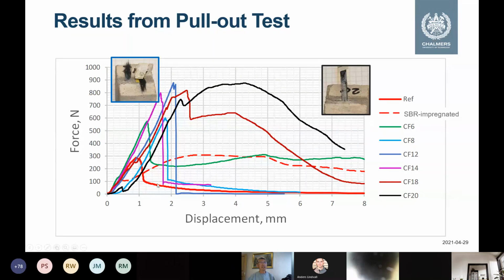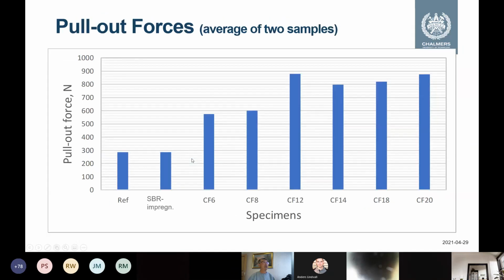The red one is the ordinary fiber without nano treatment. But all of the nano impregnated fibers show much higher pull-out strength and also a much longer displacement, which is an indication of very good bonding. This one is a commercial SBR, a kind of rubber impregnated fiber. But our nano impregnated carbon fiber is still much better than the commercial one. The pull-out force is increased by 2 or 3 times.